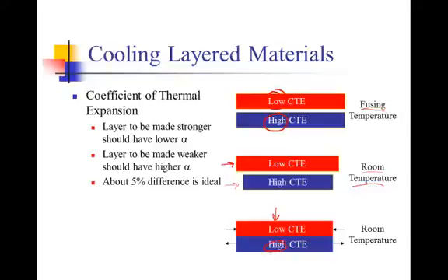I mentioned that the surface is slightly lower in coefficient of thermal expansion. It's important that it not be much lower. About 5% is the limit. We can make the material stronger and stronger up to the point where there's a 5% difference.